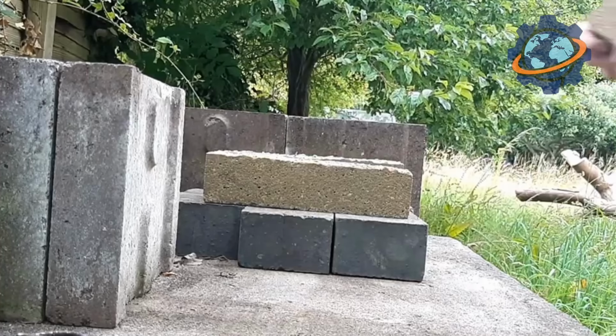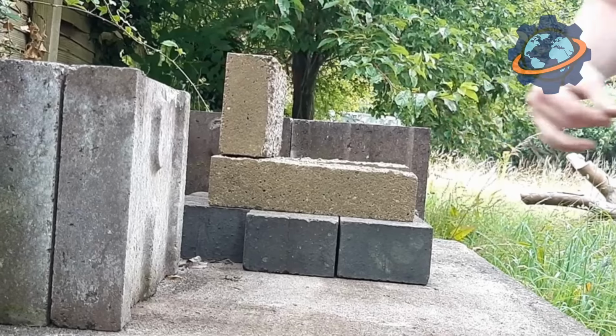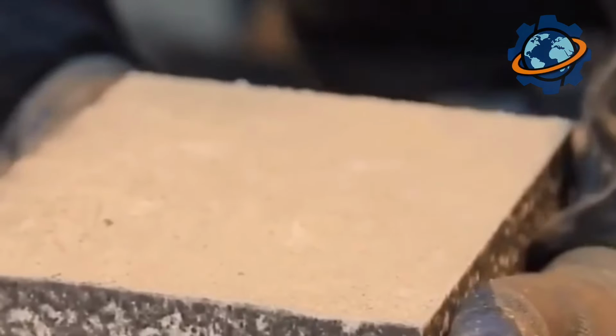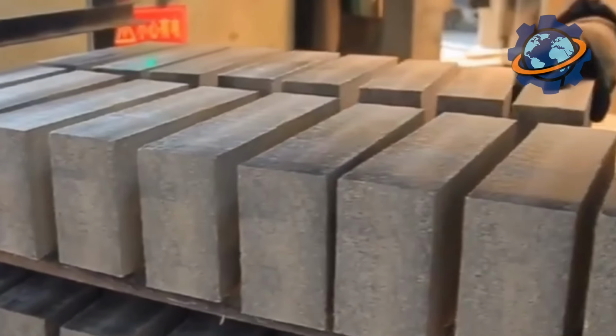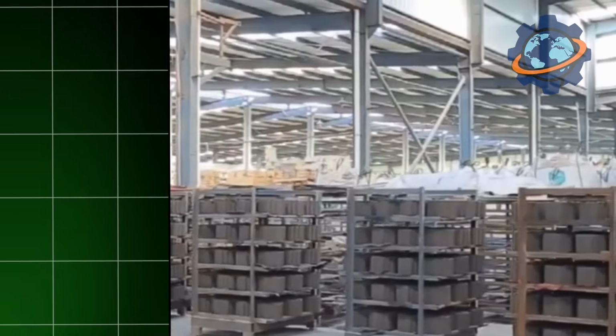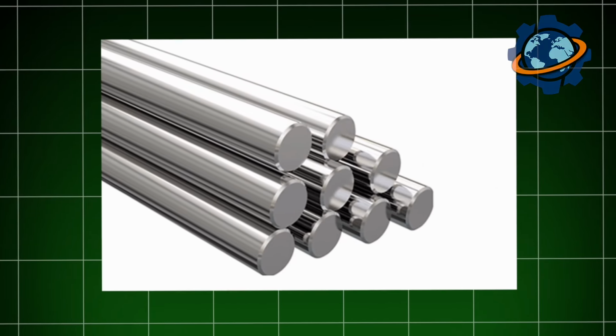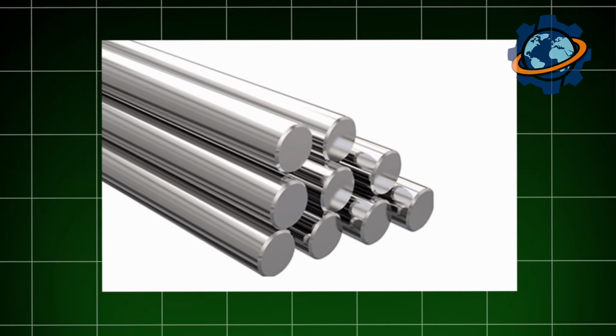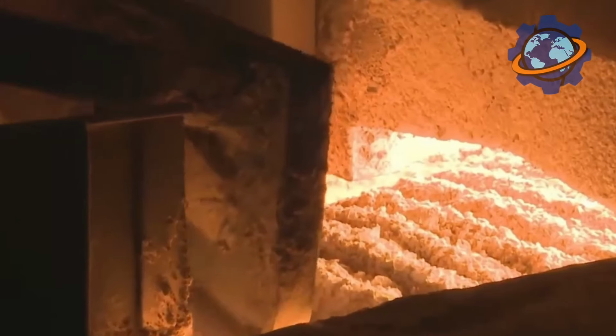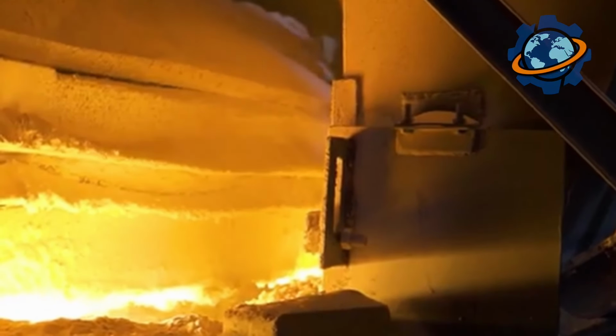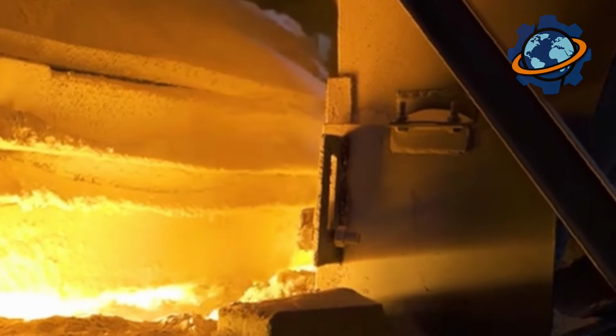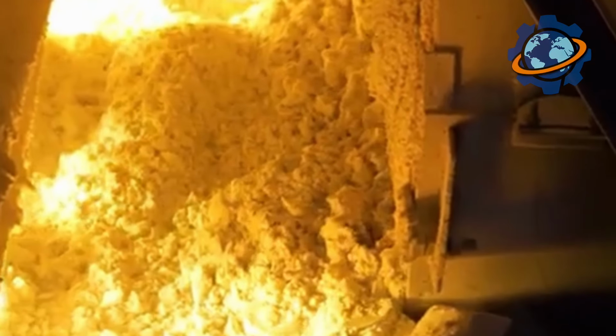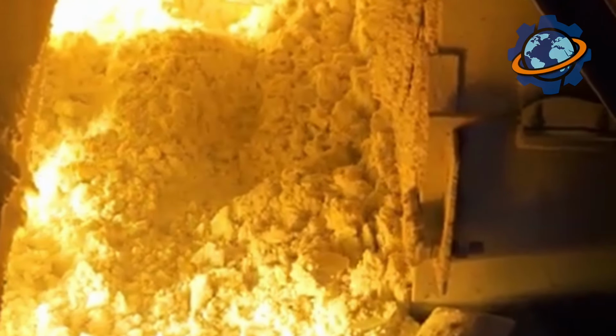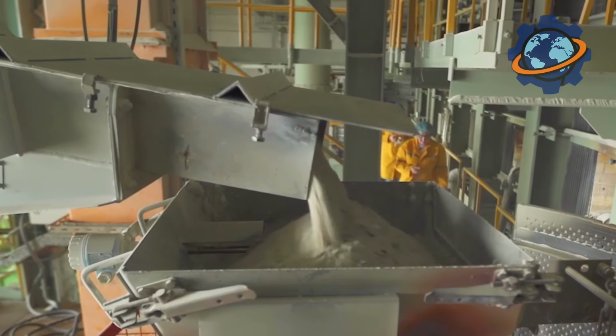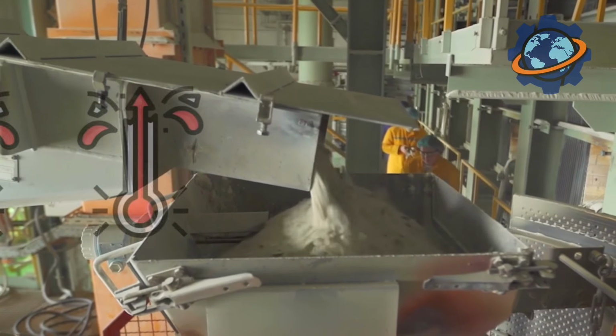Refractory bricks are used to line the inside of blast furnaces, where pig iron is born from ore. They are used to line oxygen converters and electric arc furnaces, where pig iron is transformed into steel. Huge steel teeming ladles that transport molten metal are also protected on the inside with a lining of refractories. Moreover, for each zone of the unit, its own special type of brick is selected, capable of withstanding not only temperature, but also the chemical aggression of the melt and slag.